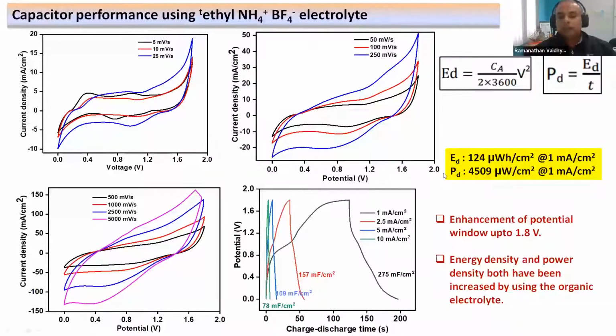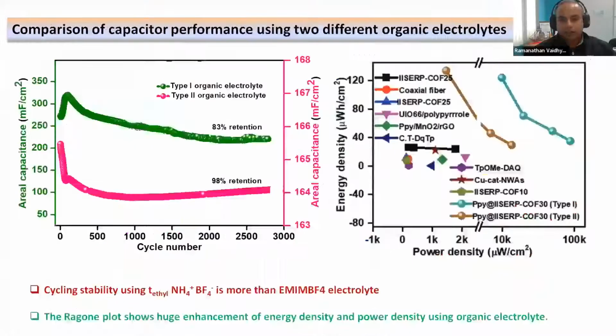Okay, and you can see when we translate this capacitance into the energy density, we are able to get excellent energy density and simultaneously very high power density. And this is exactly what was our target. So if you look at this, this is where we are sitting at the energy density, and this is where we are sitting at the power density. So we are exactly reaching this corner of the Ragone plot, which makes your material behave more like a combination of supercapacitor plus a battery.